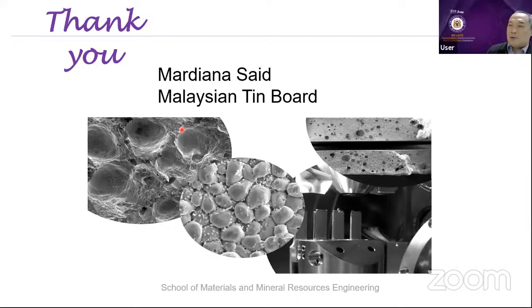Okay, that's a very good question. This field we consider as composite solders. There are many reports saying that these nanomaterials can improve the mechanical properties. But on our side, we found a problem with the nanoparticles: because the density of the nanoparticle is lower than the density of the metal, they tend to go to the outside of the solder itself, meaning on the surface, and are not part of the IMC. That is something we can explore more, or find the best nanoparticle that can be embedded closest to the IMC itself.